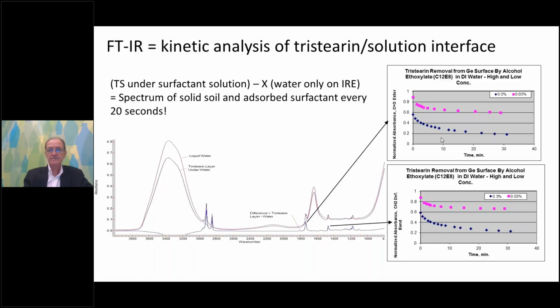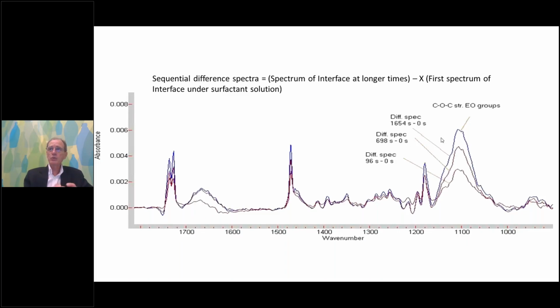Well, why is that? Well, we can do one more subtraction. We can take the spectrum of the interface at any time, and we can subtract the very first spectrum from the spectra at longer times. First spectrum times some scalar, and if nothing happens at the interface, we should be able to null out the complete spectrum and get a straight line. That's not, however, what we see in the experiment.